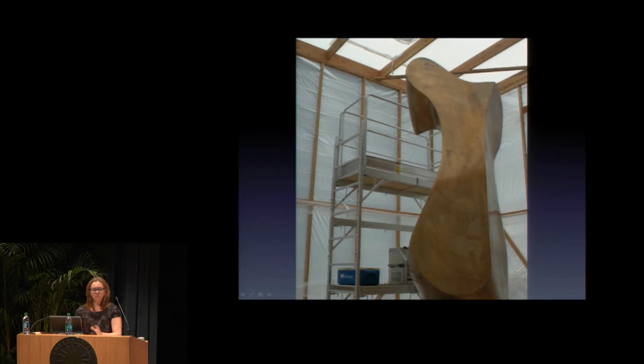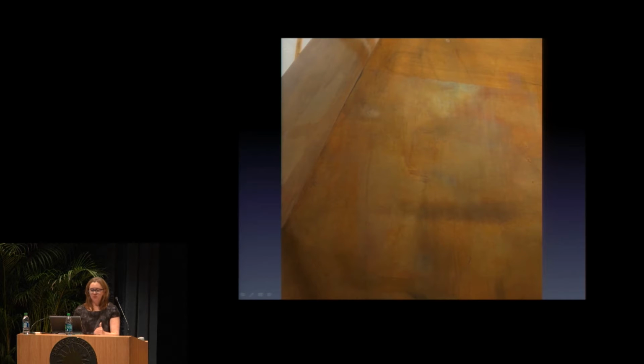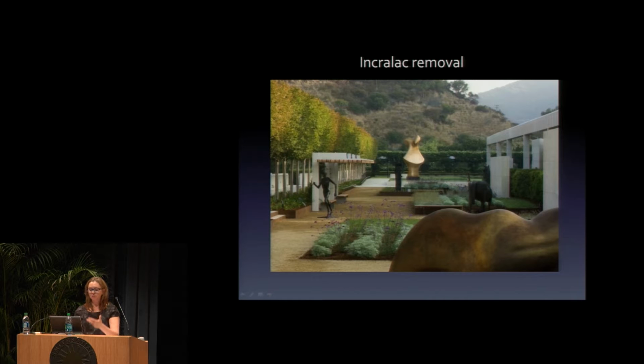So the treatment was done inside the tent, and applying, I believe it was Safety Strip, they applied first for about 15 minutes and then used the carbon dioxide to clear it. So on the bottom, you can see where all the coating has been removed. On the top, there's still some polyurethane. And it was a very kind of clean process. And it was recoated with Incralac, but it was a very successful treatment.